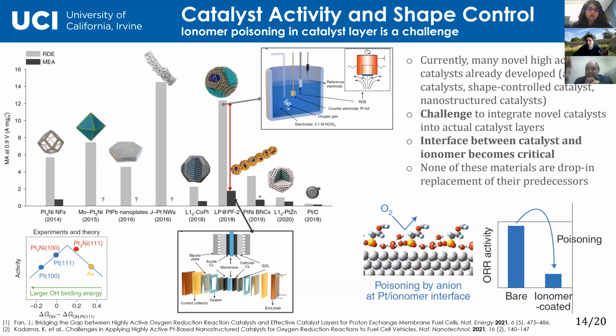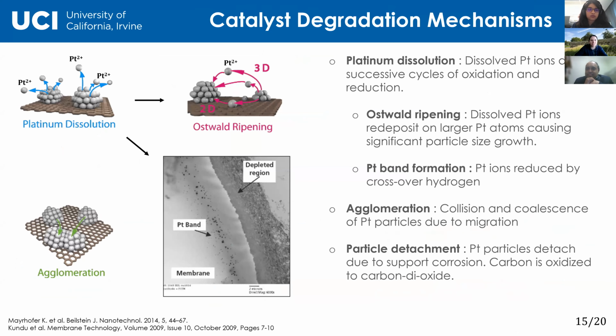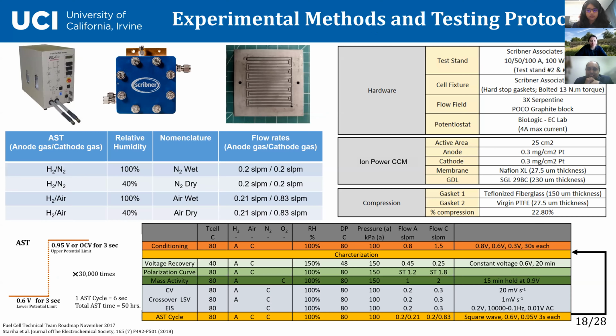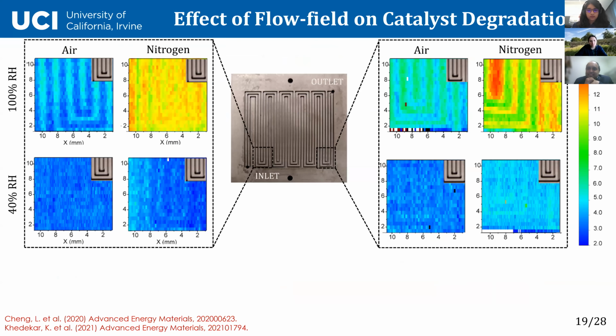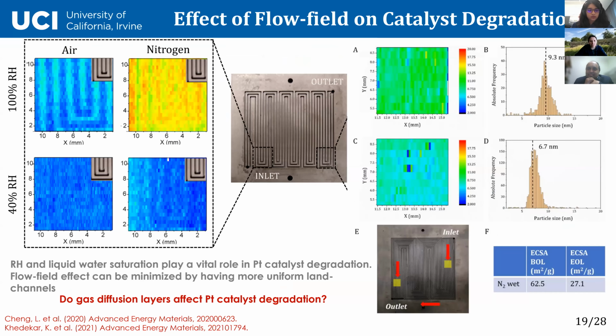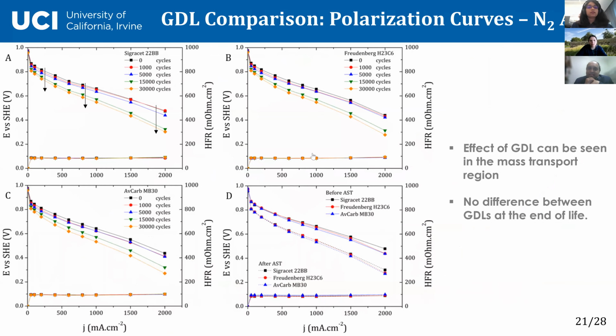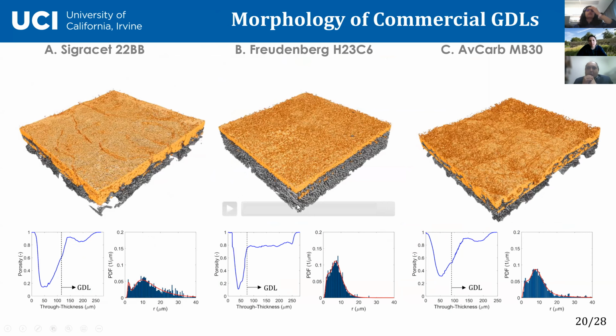Then the interface. It's interesting because gas diffusion layers have microporous layers for fuel cells. It's been years, 20 years or more, right? So you have this fine microporous layer on top. The electrolyzer industry currently just uses titanium mesh or sintered titanium without a microporous layer. So you have very bad contact between the porous transport layer and the catalyst layer.